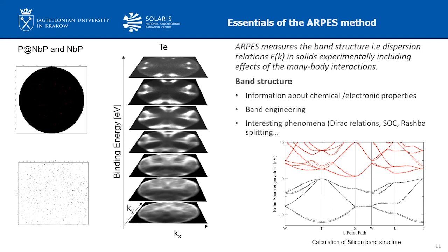The dispersion relation is periodic in the reciprocal space. A conventional way to present a very limited but essential part of the dispersion relation is drawing it along a certain path connecting high-symmetry points in the Brillouin zone, as presented here for the calculated data for silicon.